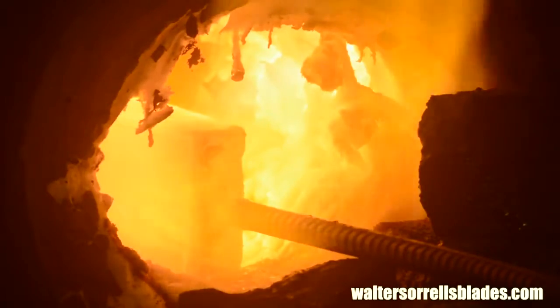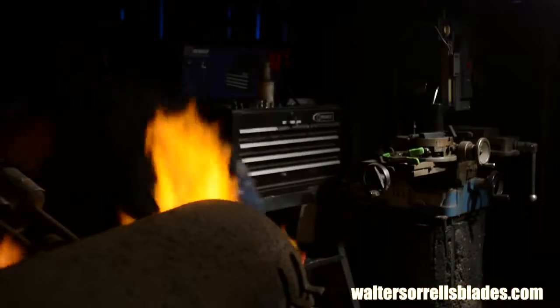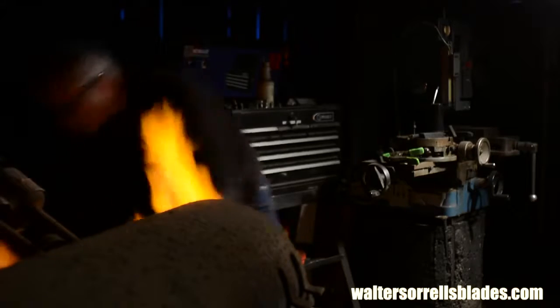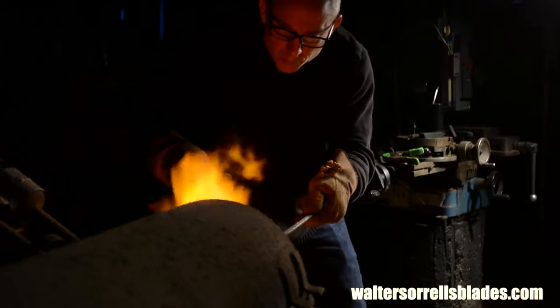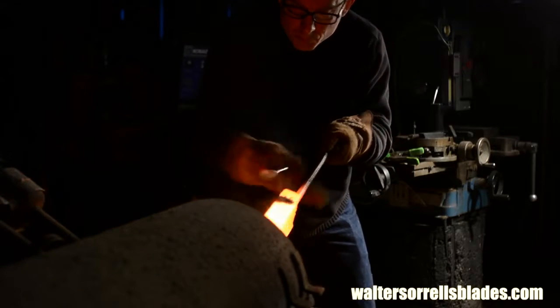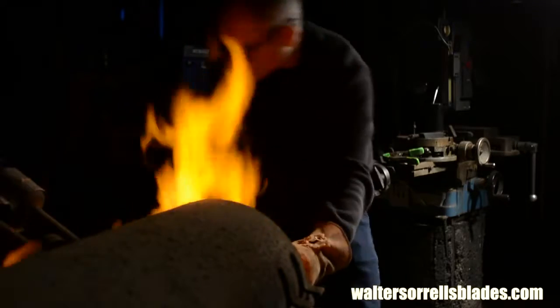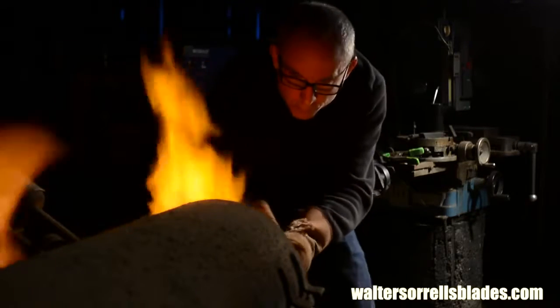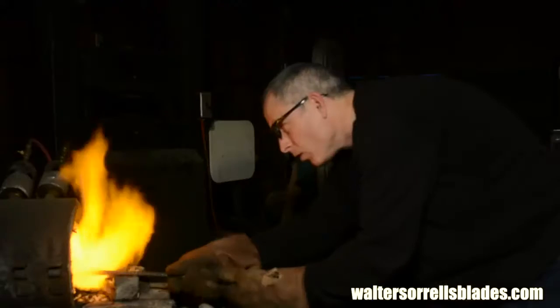As the flux melts, it flows and covers the whole billet. You want a nice wet layer of flux around every single inch of the billet. Capillary action will draw it right through the layers. I usually hit it up with a couple more spoonfuls of borax as it's coming up to temp, just to make sure that it doesn't boil or drip off. Maybe it's overkill, but hey, I'd rather waste a little borax than end up with crappy welds.